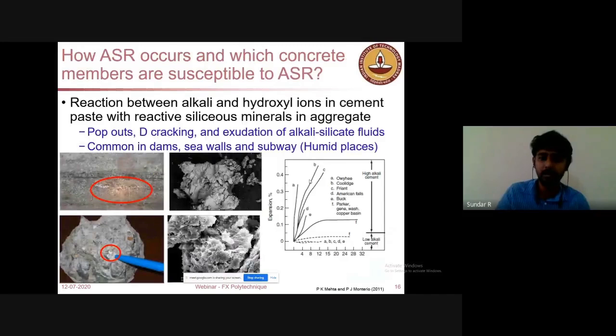And the next one is alkali silica reaction, which is predominant in locations where the aggregates are more reactive. Reactive aggregates, in the sense the aggregate will have some strained form of silica, will react with our concrete and then form some silica gel. If you see here, these cracks are pertaining to ASR, and these white dots are the silica gel which was formed and magnified.